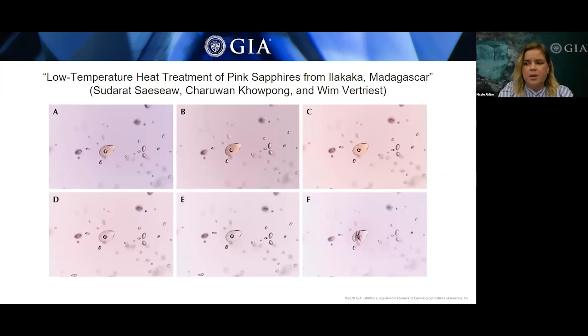And so during the low temperature heat treatment, these inclusions show no change when heated at 800 degrees Celsius for 160 minutes. Some epigenetic iron staining did get darker due to the presence of oxidation.